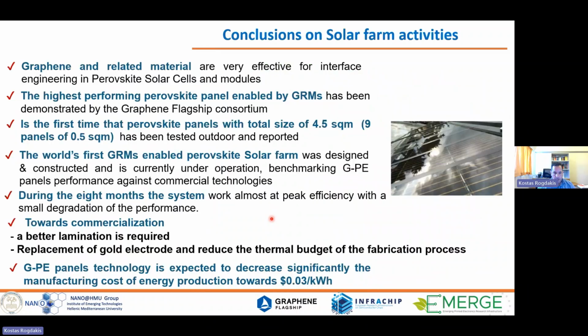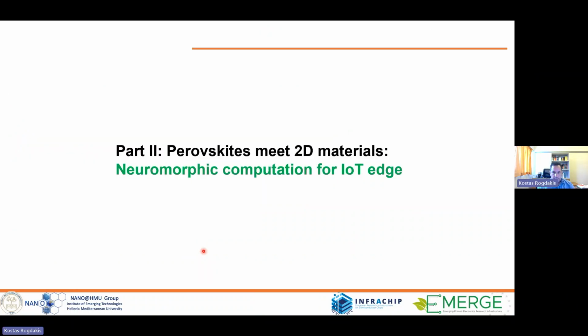Okay, so to sum up, we demonstrated the first farm in the world using a perovskite technology that is printable and also integrated into the materials. For the first 8-9 months, we have very good stability of the technology, but afterwards we noticed a lamination failure of the panels that started the degradation of the performance. LCA also indicated that we have to replace gold with other more sustainable materials like carbon-based or graphene-based electrodes. And we're still working on this technology.